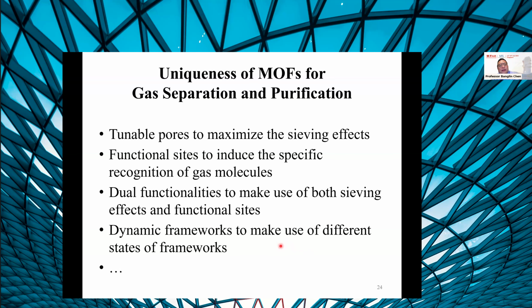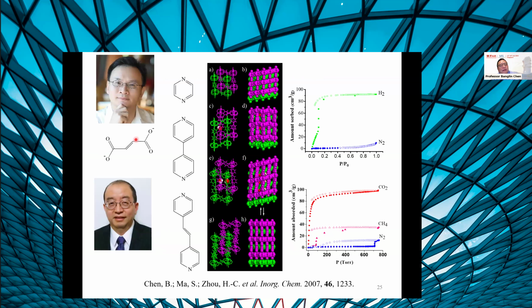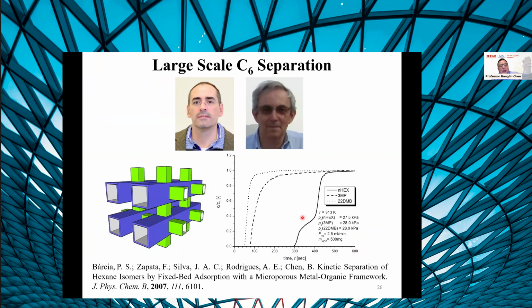So I will show you several examples. This is one example using the same organic linker, but a different pillar. So the structure is isostructural, the pore surface systematically tuned, and this can be shown in sieving separation. However, the interaction with this gas molecule is kind of weak, which means separation is only realized at a low temperature. And the ideal one is for separation at room temperature.